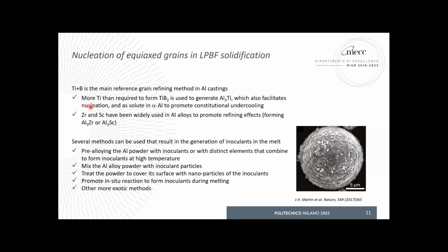But also zirconium is used, also scandium is used, and many other exotic elements can be used. Again, they generate Al3 aluminides of zirconium or scandium that act as inoculants for the solid phase of the aluminum. How can we put those inoculants into the powder? Because we cannot forget that we are not talking about casting anymore. Here we need to talk about additive manufacturing, and in general, I will be referring to laser powder bed fusion processes. So what we can do is to pre-alloy the powders. We start from a melt that already contains aluminum, the alloy elements for the aluminum alloy, and for instance, the titanium and boron. And then we produce the powder, which is a pre-alloyed powder, and then we use the powder that already contains intrinsically the inoculants.